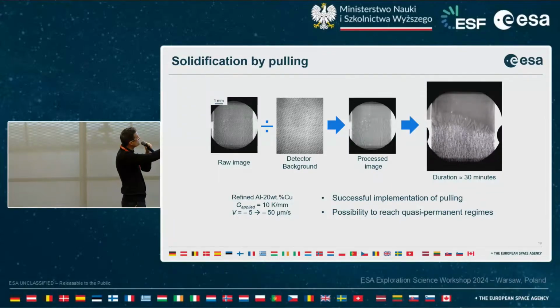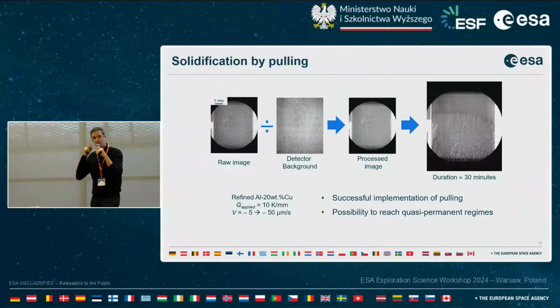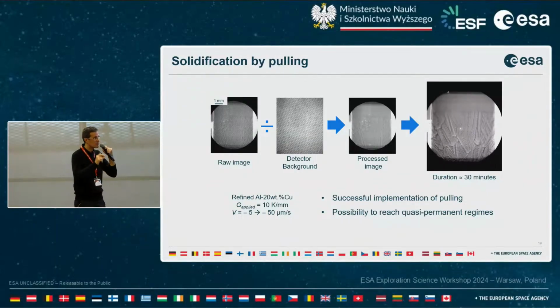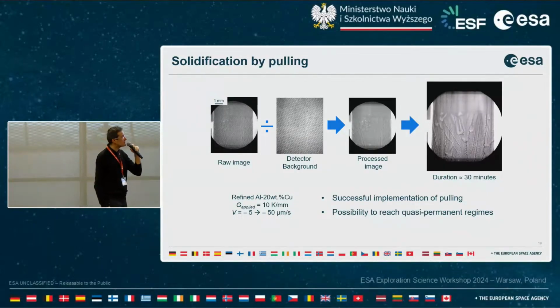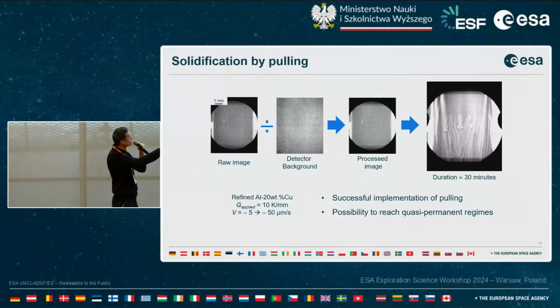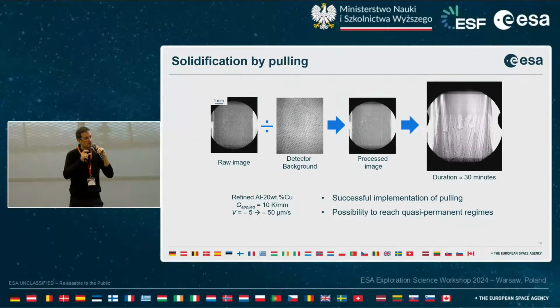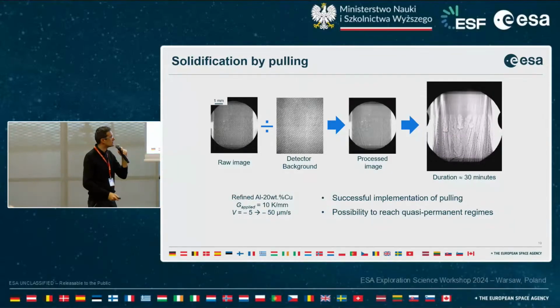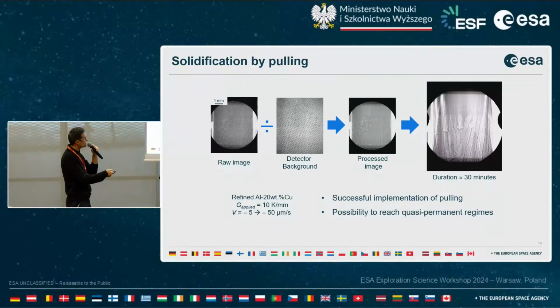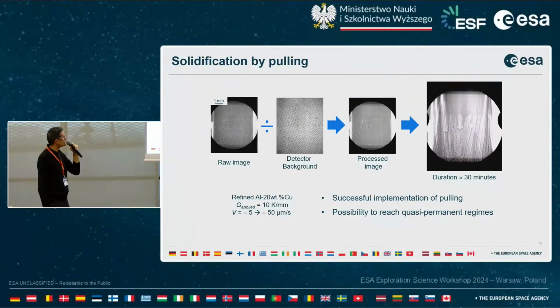You could see here the solidification front that is slightly curved. Maybe you can see that here it's lower than here, and this is typical of convective flow occurring during the solidification. So even if the samples are rather thin, there is still convective flow. And when we increase the solidification velocity, then the front is flat again, because we have to find a ratio between the characteristic velocity of the convective flow and the characteristic velocity of the solidification. And so hopefully it will be possible to reach quasi-permanent regimes during such an experiment.